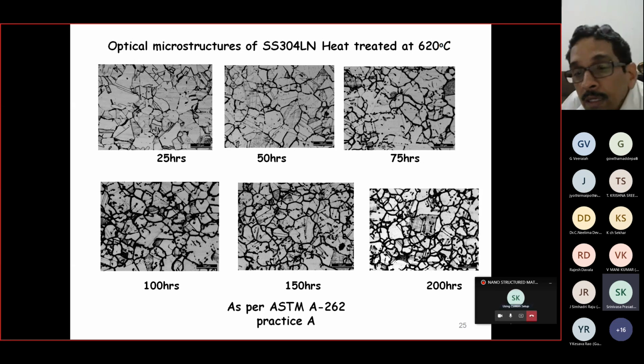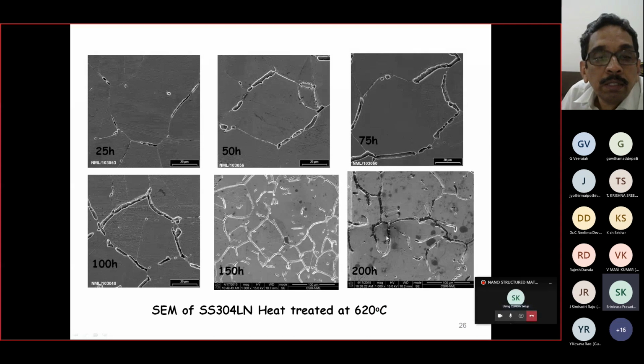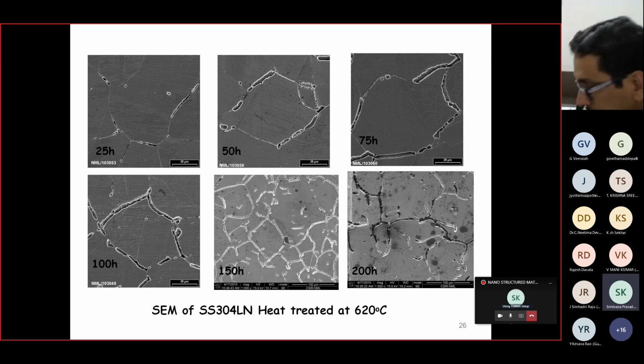Now, I think all these microstructures are at the same magnification, at 100 microns. This is seen clearly, but we are not able to estimate the size and how it behaves also. We have only seen that the magnetic behavior is different. So we have to confirm that the dark lines are only of nanometer size. How do we go about it? See, this is a typical SEM microstructure.